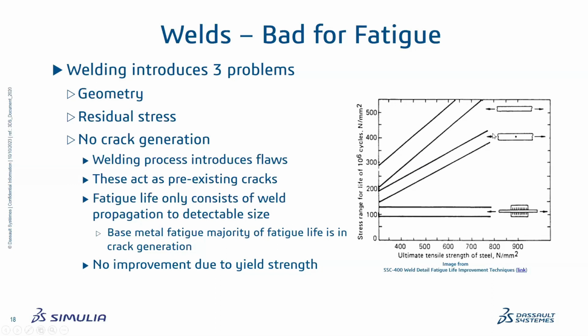And it also leads to this kind of thing, which shows a difference between welded structures. With base metal fatigue, you can increase the fatigue life by increasing the material grade. Basically, the higher the UTS, the harder it is for that first crack to generate, and so you get an improvement in life. But if you're taking that aspect away because you're welding it, then increasing the material grade of your steel hasn't influenced anything at all because it's just the crack propagation stage.